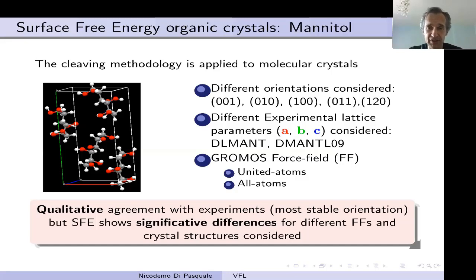And only recently we realized that there is a very big difference in terms of which force field is being used. When we use all atom force fields, which are expected to be more accurate, we were getting these big discrepancies. But more recently, we decided to try united atom models from Gromos. And it turns out that they seem to give results which are much more consistent with IGC results. So next slide, please.